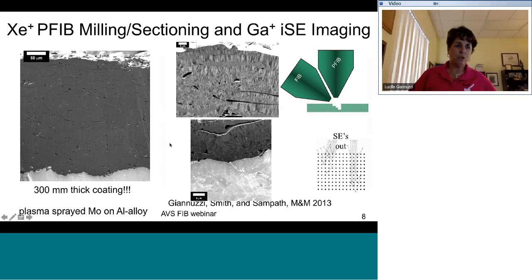You can also FIB image your 2D section. This was on a FIB type instrument, but you can also use the FIB on your instrument to image inside the trench. This generally requires a 180-degree sample rotation to look in there. On a single beam FIB, this just requires a single tilt.